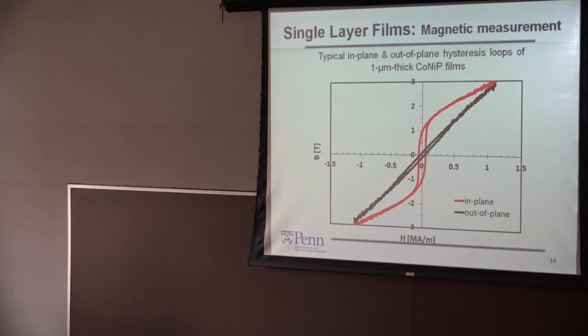So after the optimization, right, what do we get? So here is the 1 micron thick single layer cobalt nickel phosphor film measured by VSM to check the magnetic properties. So as you can see, as desired, we have a relatively large in-plane BH max compared to the out-of-plane, and also the magnetic anisotropy lies in the in-plane direction.